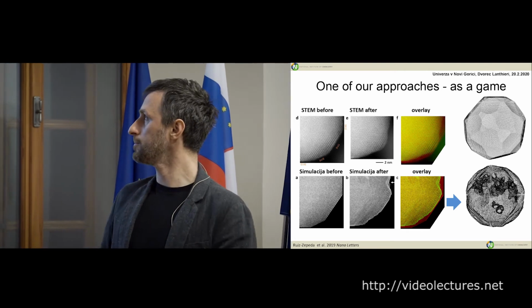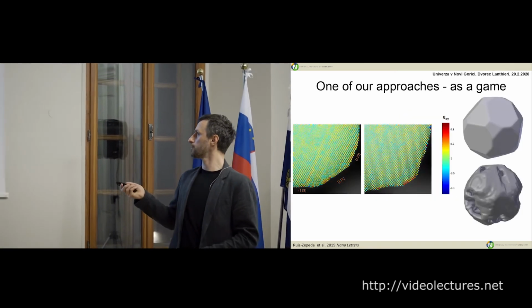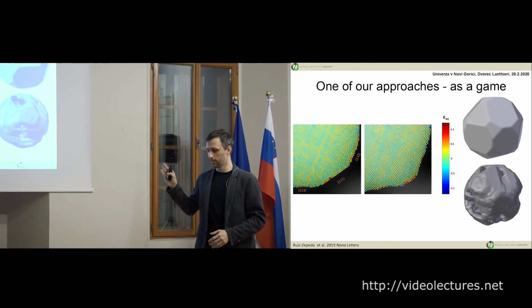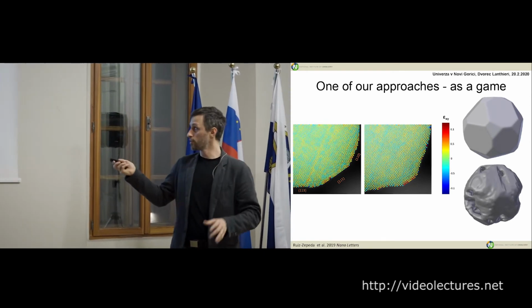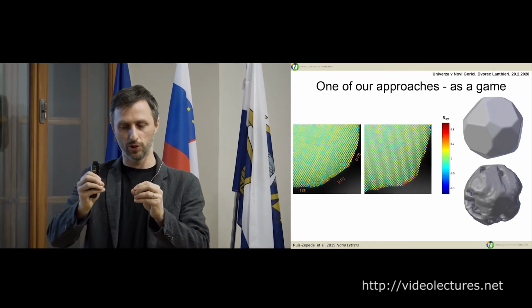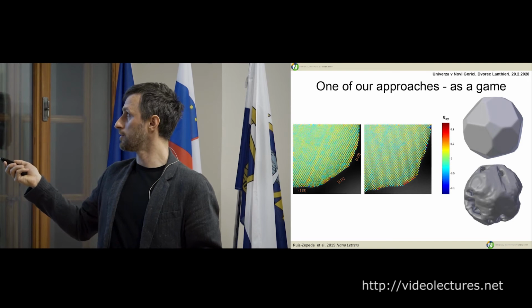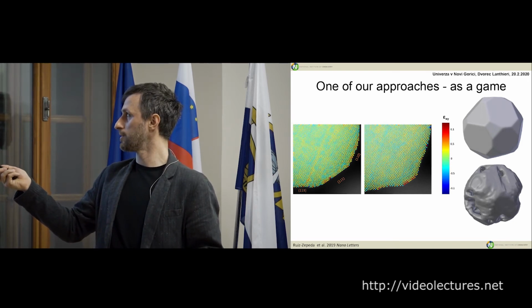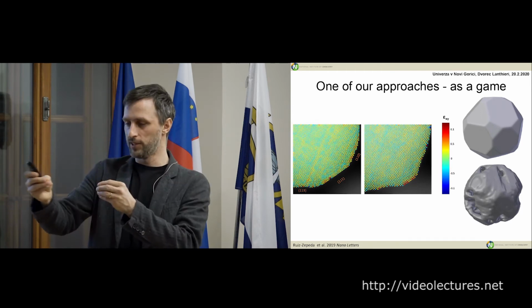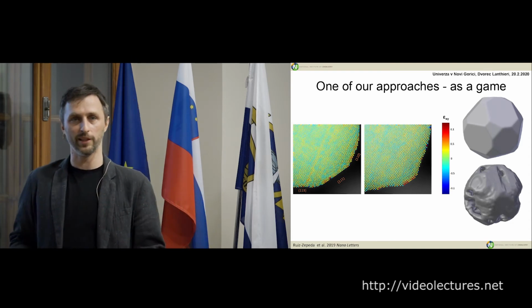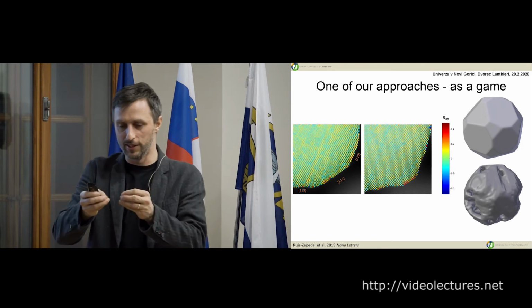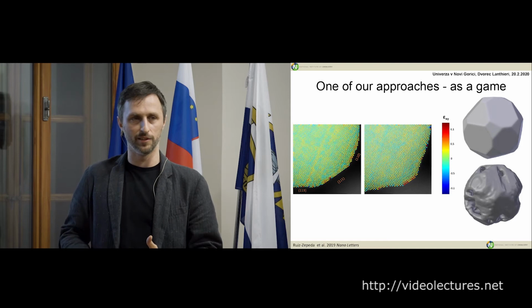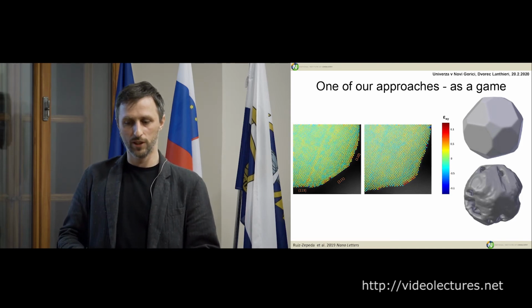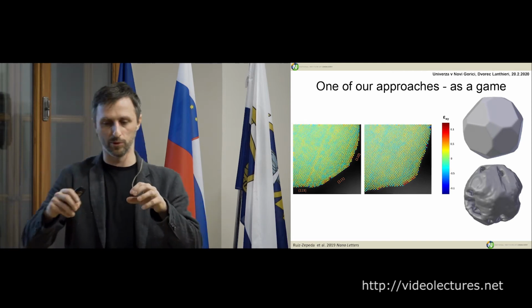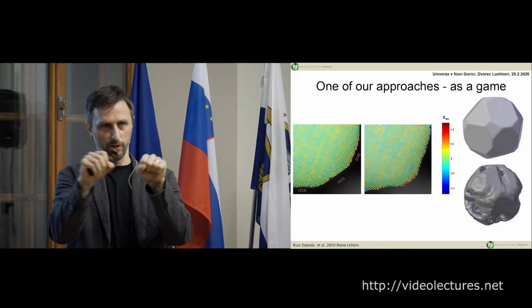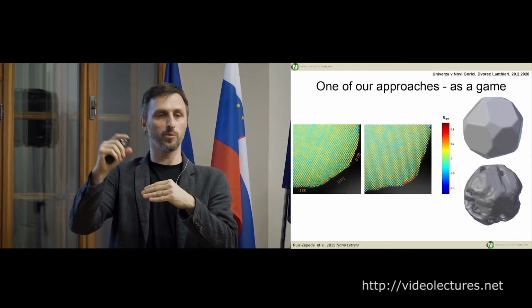You can also make this surface model to see the pore formations, but what I think is very interesting is this geometric phase analysis. So this is just the positions of atoms, and if there's some straining, so changing in the positions of atoms, you just see it as a color. So you're comparing the distance to different atoms, and then if the distance changes, you change the color of the atom. So it's called geometric phase analysis. Why is this interesting? Because the distance between these atoms in platinum has a big effect on the activity. It's called strain effect. And this is how the whole community is tuning the activity. So this is why we put copper under platinum. Copper is smaller, it strains the platinum together, and this then gives appropriate adsorption energy for the reaction.